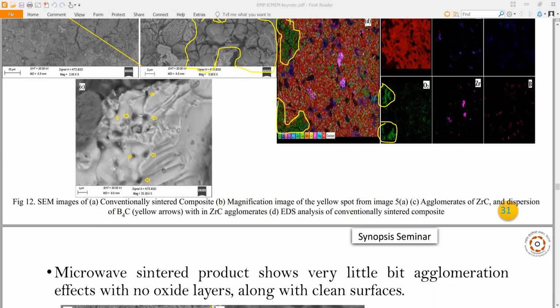This is SEM images, same images of A, conventionally sintered composite. B is magnification image of the yellow spot from image 5A, and C, agglomeration of ZrC and dispersion of B4C, yellow arrows with ZrC agglomerations, and D, EDS analysis of conventionally sintered composites.